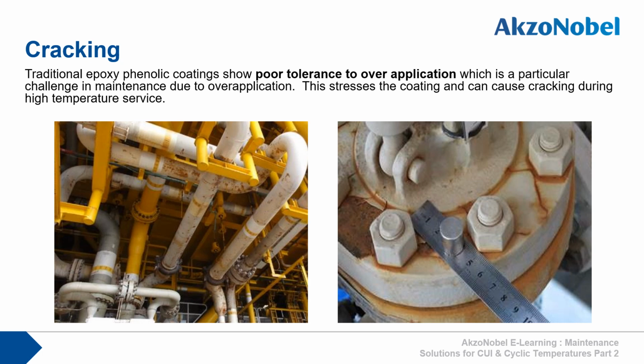Again, if we look at traditional epoxy phenolics, we see that they tend to have poor application tolerance, and datasheets often state maximum scheme DFTs that must not be exceeded for fear of crack formation. Sometimes cracking is not seen after application and will only show itself once the coated steel is back in operation. If this coated steel is insulated, we will never know what is happening, and so the CUI risk now becomes very high indeed.